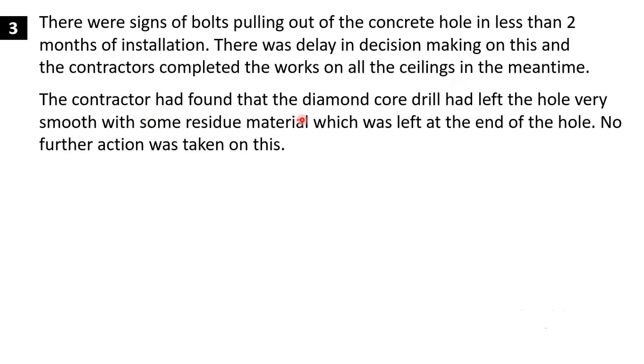The contractor had found that the diamond core drill had left the hole very smooth with some residue material which was left at the end of the hole. No further action was taken on this. A very smooth surface inside the hole is not good for bonding between epoxy and the concrete. Again, any residue material left inside the hole will also cause problems in the bonding between epoxy and the concrete.